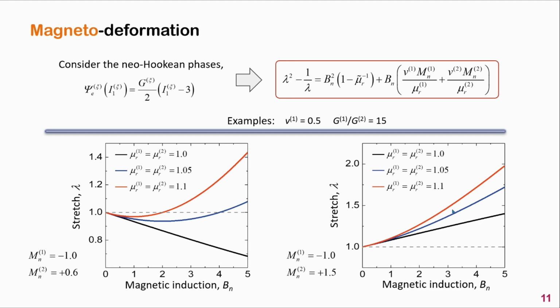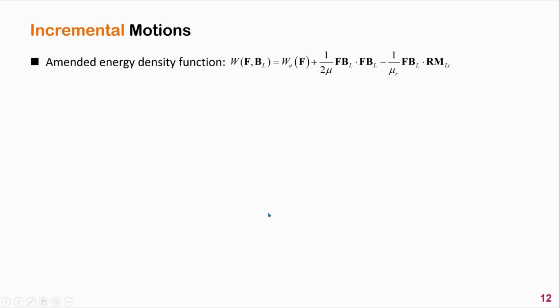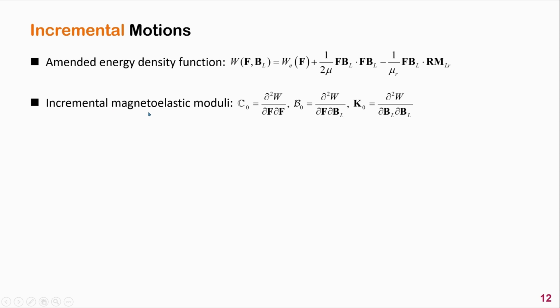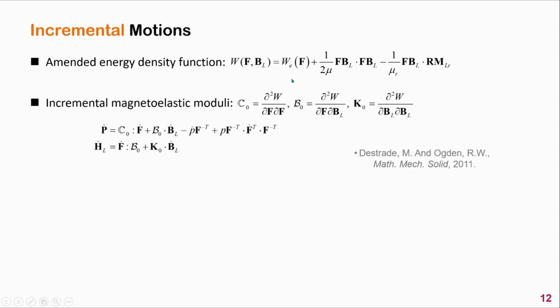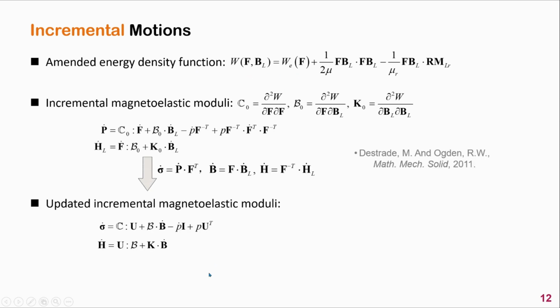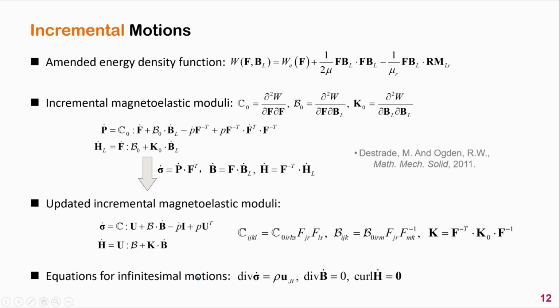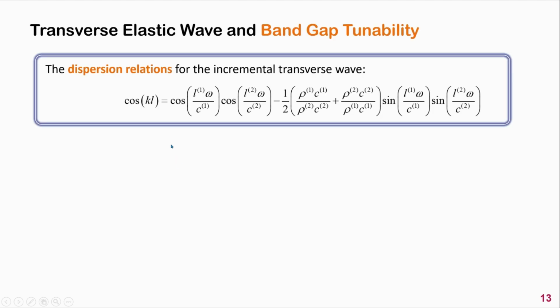Okay, the laminate has been deformed under external magnetic field. Now we consider incremental motion superimposed on the deformed state. Using the incremental magnetoelastic moduli obtained through the augmented energy density function, we can finally obtain the equation of motion for the incremental waves as shown here. Then, by applying the Bloch wave theorem, we can obtain the dispersion relations for the incremental waves. Here, we focus on the transverse wave.